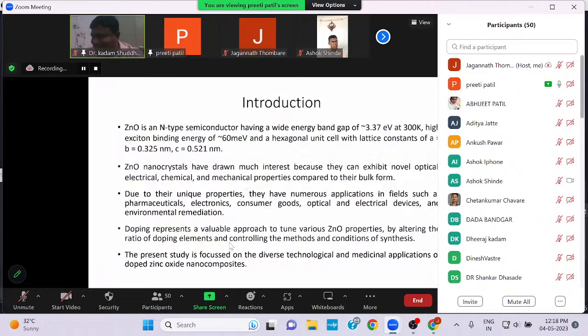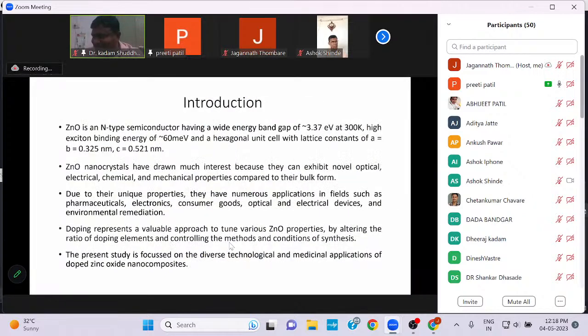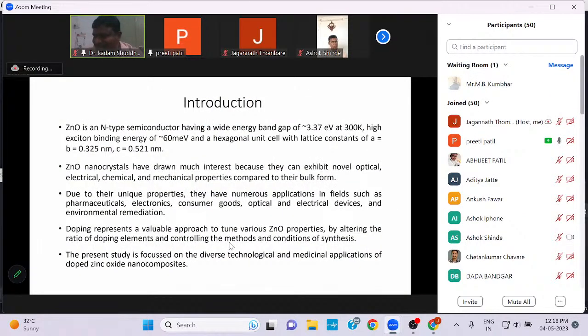To start with, I would like to give some introductory notes on zinc oxide nanocrystals. Zinc oxide is an N-type semiconductor having a wide band gap of nearly 3.37 electron volt at room temperature, a high exciton binding energy of nearly 60 meV, and a hexagonal wurtzite structure with lattice constants a = b = 0.325 nanometer and c = 0.521 nanometer.